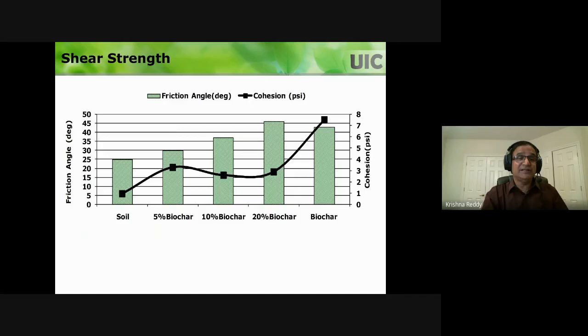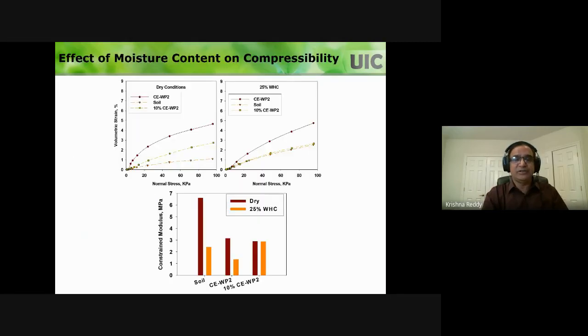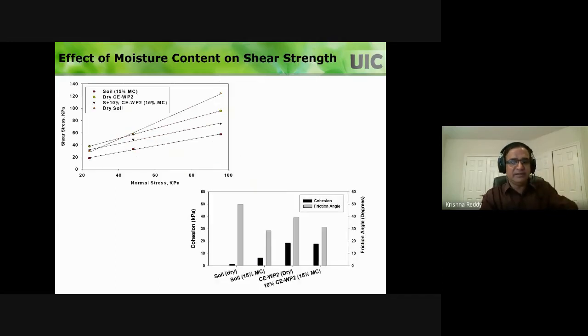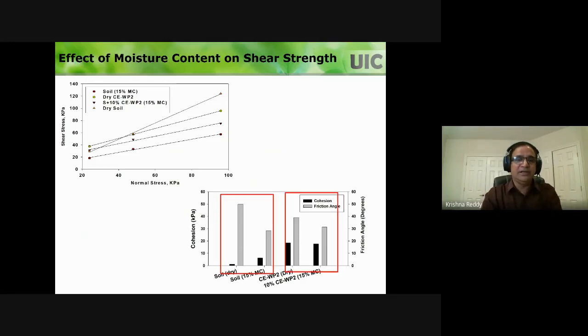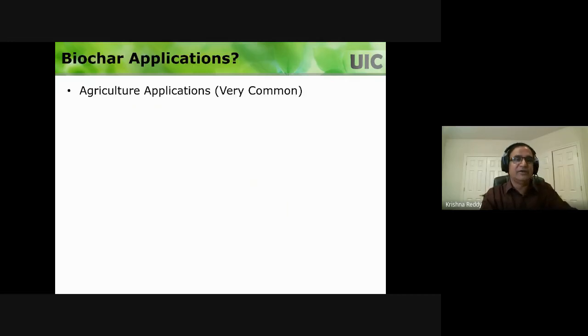In terms of the shear strength, surprisingly, the biochar has a higher shear strength, and even if you add this biochar to the soil, the shear strength is going to increase. That's a positive aspect. But moisture content makes a lot of difference. If you test the dry biochar versus moist biochar, you will get different results. So you will see that generally when you have moisture content, the strength is going to decrease. So you need to have those properties at hand when you think about biochar applications.